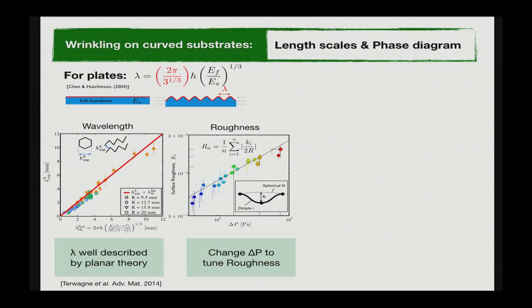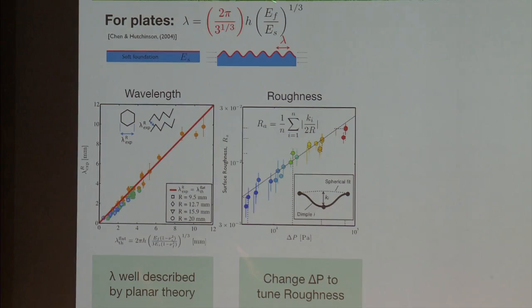So first of all, if I plot the wavelength that we get in our experiments, as a function of the prediction for flat plates, you have a y equals x line. And so basically what we get on our curved system is exactly the same for the length scale, for the wrinkling wavelength, as what people have calculated for flat plates. So that was a bit of a disappointment. On the other hand, we now have a design guideline. If you want dimples of a certain size, we know how to get them.